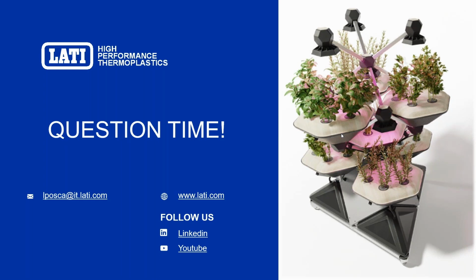Let's say 15% glass and 35% glass, and then you put 40% graphite in the first one and 20-30% graphite in the second one. So you can mix graphite and glass fibers. You will have a compromise. You will have a better thermal conductivity, but you will not have a properly thermally conductive product. You will have something that stays more or less in the middle.